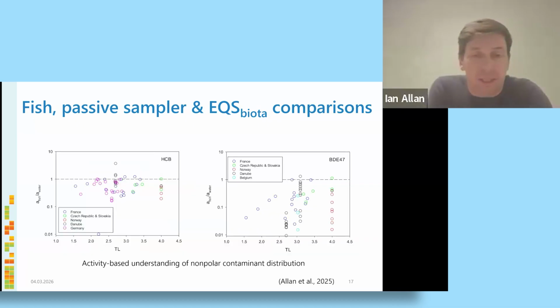So we tried to assemble data that existed through different studies conducted at different sites. And here we've got hexachlorobenzene, HCB on the left, and then we've got BDE47, polybrominated diphenyl ether on the right. The scale, the y-axis, is essentially the activity in the fish divided by the activity in water. So what it means is a number that's above 1 is telling you that the fish is more concentrated than the water.